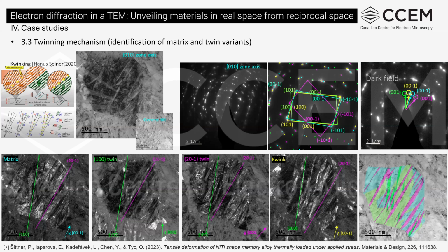So at the very beginning, when I was making the TEM foil using the FIB, I have to make sure the bulk material is correctly oriented so that the 010 direction could be achieved in the TEM. Because the TEM has limits of tilting, when the TEM foil was made, I have to perform hunting for a specific zone axis, because from zone axes other than 010, we cannot observe the result of kwinking.